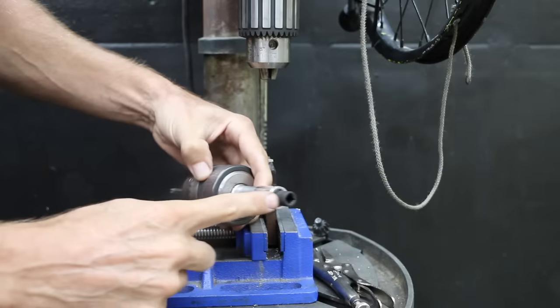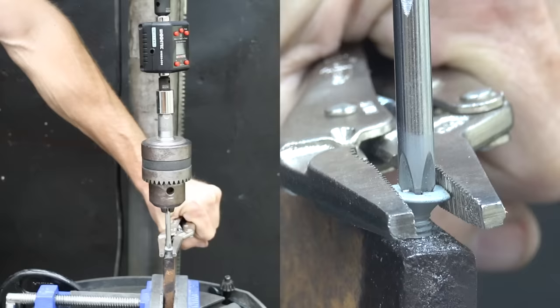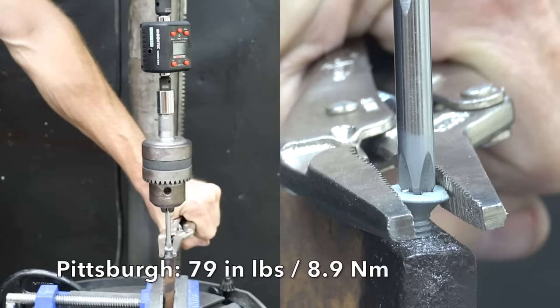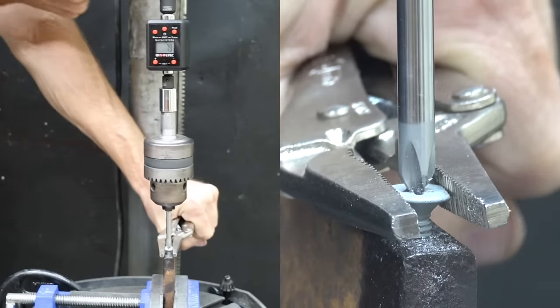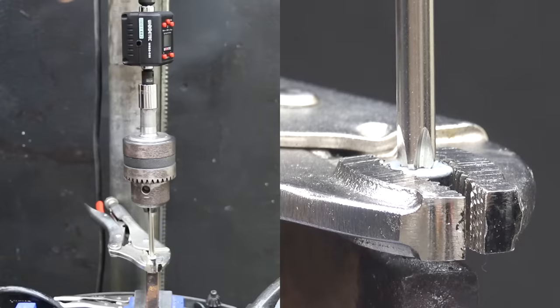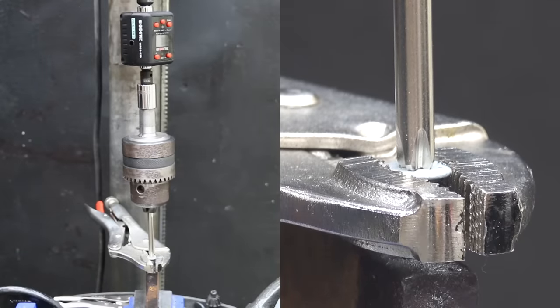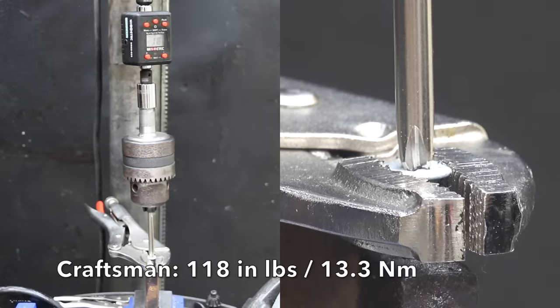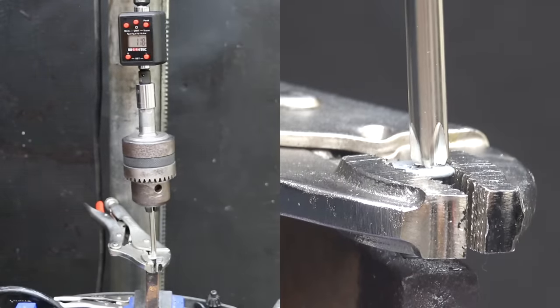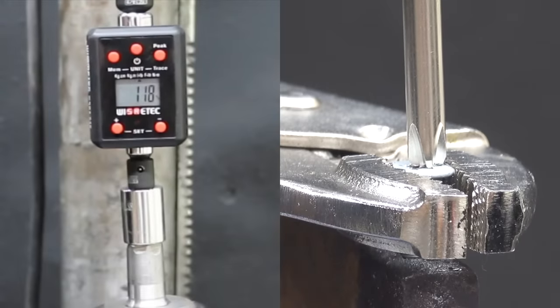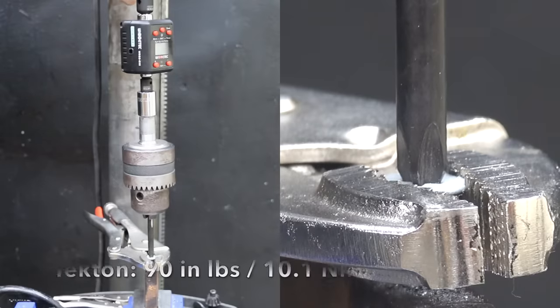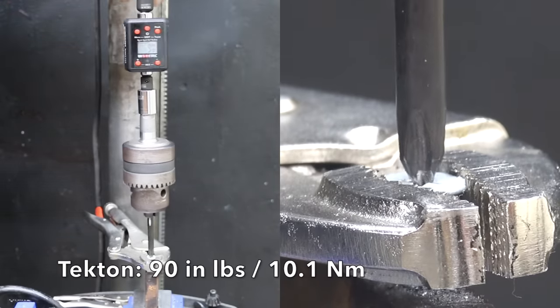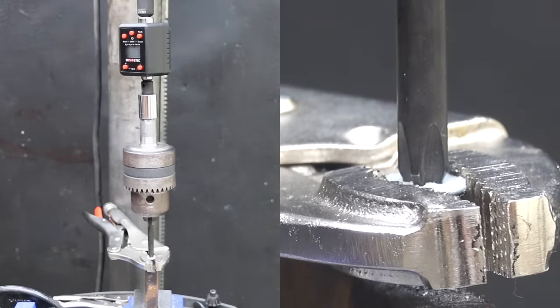Even with 100 pounds of downward force, and after only driving 12 screws, the Harbor Freight Pittsburgh cammed out at only 79 inch pounds. I guess you get what you pay for. After installing and removing 100 screws, the very affordable Craftsman puts up 50% more torque than the Pittsburgh, finally snapping at 118 inch pounds. Very impressive for a budget tool. After installing 20 screws, the Tekton cammed out at 90 inch pounds, or 28 inch pounds less than the Craftsman.